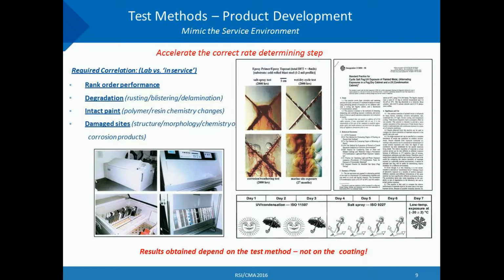And what you really can't see here, but it's a really critical point, is that far away from the scribe, out here, for example, there's a significant loss of gloss for this epoxy, just like there is here in real life, but that is not replicated in either of these two tests. So if you combine all those factors together in this test methodology, you get a good result. And it was standardized back in the 1990s by ASTM. Quick comment, the ISO organization in Europe basically uses a very similar test regime, and that's what they have standardized on for many applications, not just rail car coatings, but also oil and gas applications and so on.